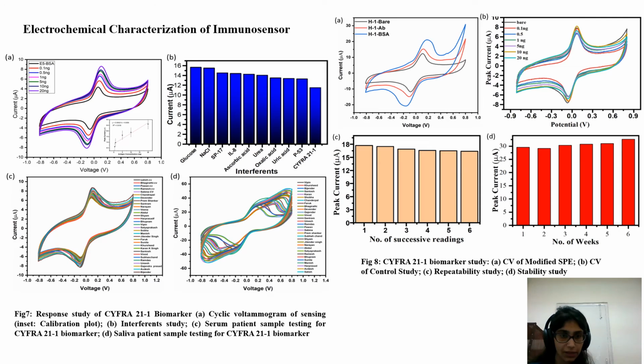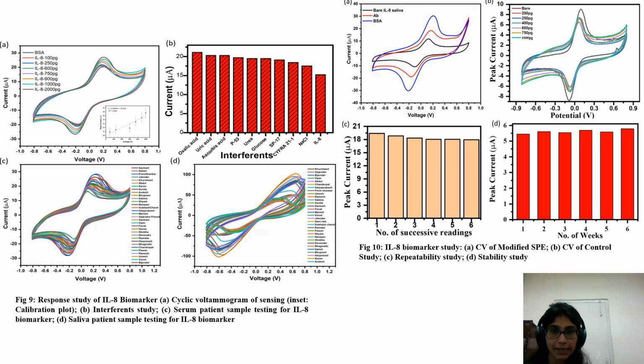Thereafter, the electrode efficiency was also tested with patient serum and saliva samples, as represented in figure 7c and d, and the electrode repeatability and stability test was done, as shown in figure 8c and d. The electrode was found to be repeatable with 6 successive readings, and also stable for 6 weeks. The control study was also performed, as shown in figure 8b, where no trend was found, as antibody was missing on the electrode surface. Similarly, all studies were done with IL-8 also. The only difference was the sensing concentration, from 100 picogram to 2000 picogram, and the rest of the results were obtained similarly to the CYFRA 21-1 biomarker.